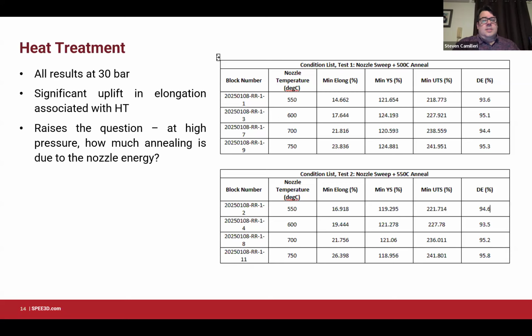Okay, a bit of analysis in general. Again, this is at 30 bar. What I'm trying to demonstrate here, which is a thing that a lot of cold spray processes don't offer the opportunity to do, is some basic heat treatments. In this case, we're not trying to sinter the material. We're just trying to heat it up a bit, improve the interparticle boundaries, relax some of the work hardening in the process. And indeed, when we do this, we do see a big improvement in elongation.